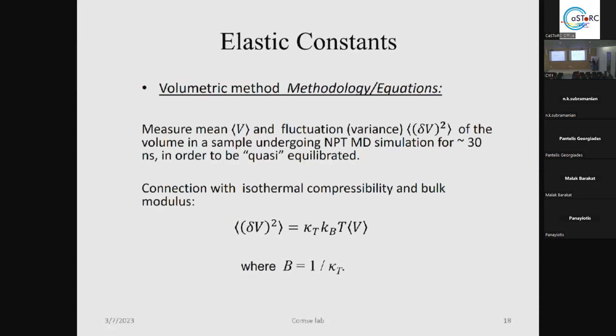As regards the volumetric method, as we know, we took into account the fluctuation of the volume, and from this we were able to calculate the isothermal compressibility, and from this to calculate the bulk modulus.